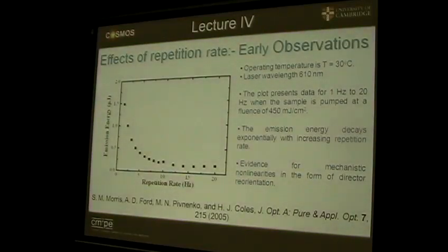We think that was due primarily to two effects. One is the optical reorientation within the system. I don't think it's heating. And perhaps photobleaching of the dye. So we thought, hey, we've got a problem here. These crystals are organics, they're no good, you can't use them. But what I want to tell you now is how you get around that problem, or you might get around that problem. The evidence in this work was that it had some kind of non-linearity.